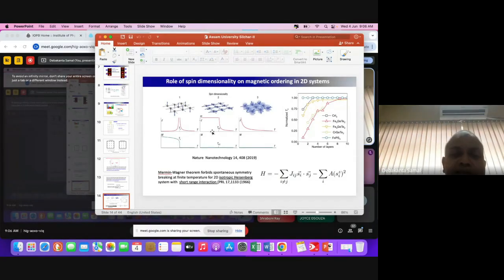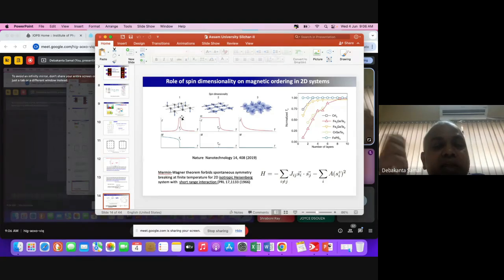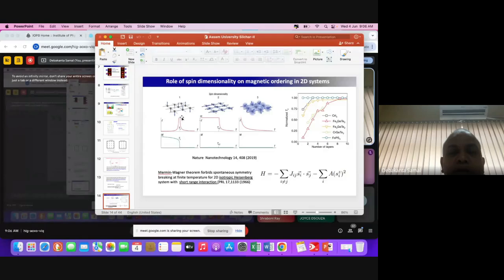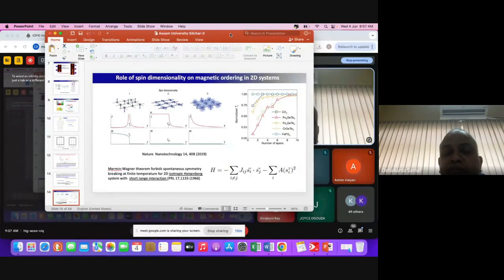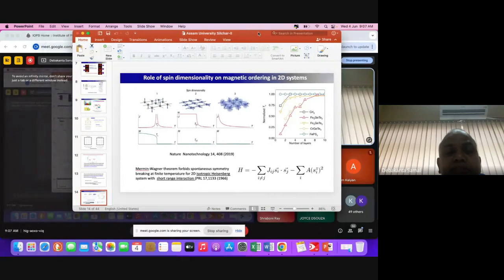But, and the last case, you see here, again the same lattice. You have like one sheet of paper, one lattice. And here the spins that you are putting have only one component. They are like Ising spins, they have either Sz or minus Sz. And now you see they have a clear phase transition here. So you can see there is a magnetization and the susceptibility diverges at Tc.